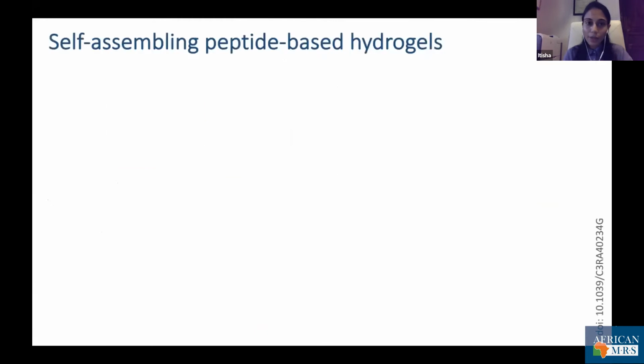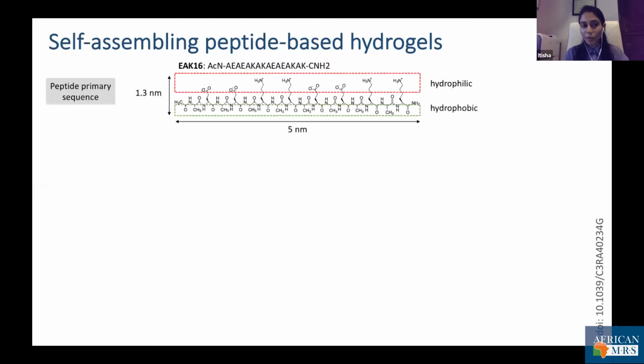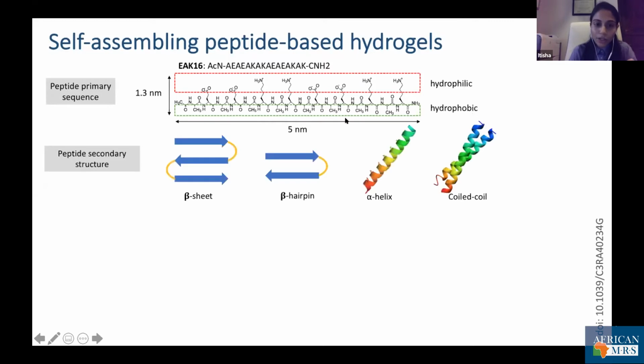Now, another emerging type of hydrogels is peptide-based hydrogels. The unique property is the gelation mechanism by self-assembling. This is an example of a peptide primary sequence. This is just one example. There are a million others. It has a hydrophilic and hydrophobic domain along its amino structure, which can rearrange into what we call beta sheets via hydrogen and hydrophobic interactions. But we also have other peptide secondary structures, such as beta hairpin, alpha helix, or coil.